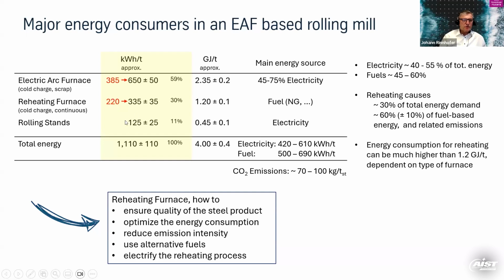And the rolling stands, they also have an electric energy consumption. And you can see that the electricity in this whole process is approximately 40 to 55% of the total energy demand of these three aggregates, and the fuel is around 45 to 60. This depends on how you run the electric arc furnace in the end, because you have different options. Either you use very low electric energy in the electric arc furnace and a high fuel rate, or the opposite. So you can also run it at very high electricity consumption with low fuel consumption, but we will never completely eliminate the fuel consumption in the electric arc furnace. So the name electric arc furnace is a bit misleading in this sense, but this is how it is.